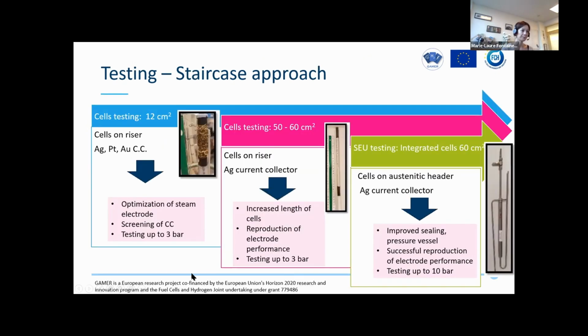So for this study, as I told you, we have gone through an iteration of scalability of the material, but also of testing. We started by optimizing the electrode and screening various current collector configurations, working at ambient pressure and 3 bar. We then moved, when we had a better understanding and robustness on the reliability of the results, towards the scaling up of the cells, still working at 3 bar to verify that we had achieved scalability by comparing performance. And from there, we moved towards the final design of our SEU and also increased the testing conditions to impose more stringent operation and see how the cell and the SEU were behaving.